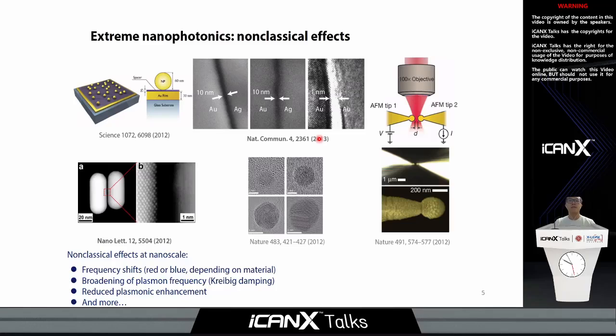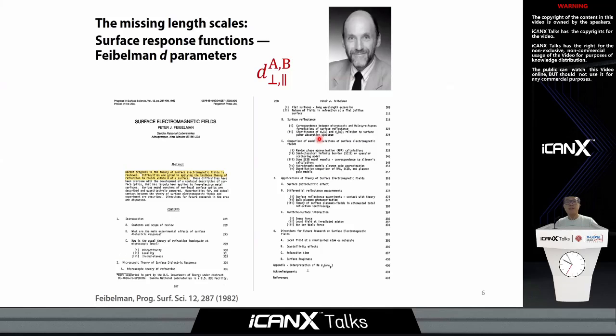field. There have also been a series of attempts to tackle this problem, but they always face a dilemma between rigor and computational scalability. I don't have time today to cover those theories, but I would like to argue that the Feibelman d parameters, introduced by Feibelman, will serve as a nice solution to these non-classical effects for length scales larger than 1 nanometer in nanophotonic platforms. This d parameter is defined for an interface comprised of materials A and B, and it has two components, the perpendicular term and the parallel term.